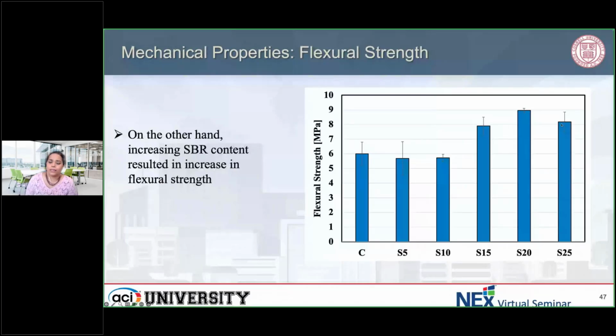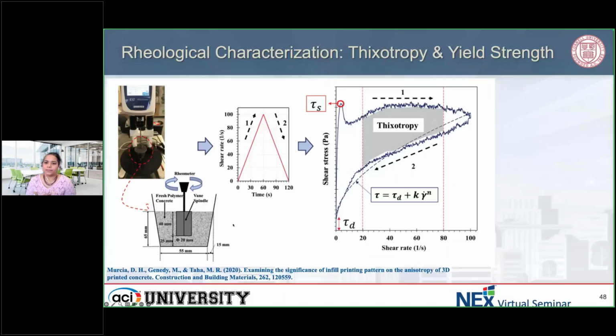So we also talked about how compressive strength is not the only thing that's important to be able to 3D print. We also need to know about the yield stress evolution, and thixotropy. So this is like the experimental setup. So we have this Brookfield viscometer, and then we do this shear ramp, and then you see what this peak maximum shear stress is, yield stress is, and then the area under the curve is the thixotropy.